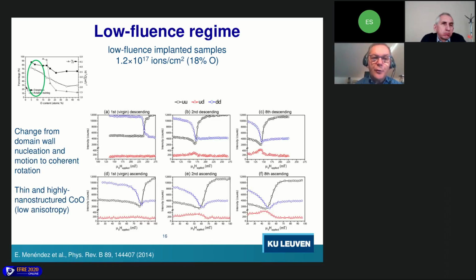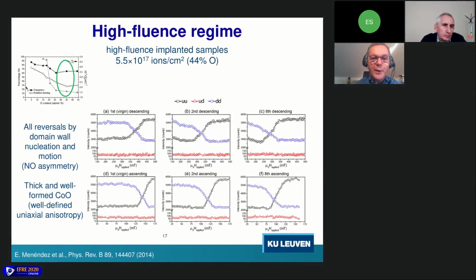So first of all, because we had noticed that this asymmetry of reversal is changing abruptly when you reach a certain minimum fluence. So here first in the low fluence regime, you can see that there is again this shift in magnetic reversal mechanism from domain wall nucleation and motion to rotation. So this is in fact the same as what is occurring in the bilayers. But then when we look now to the high fluence regime, again I draw your attention to these curves here, which are the spin flip signals. You see that they are absolutely flat. So that means that there is absolutely no rotation of magnetization occurring.